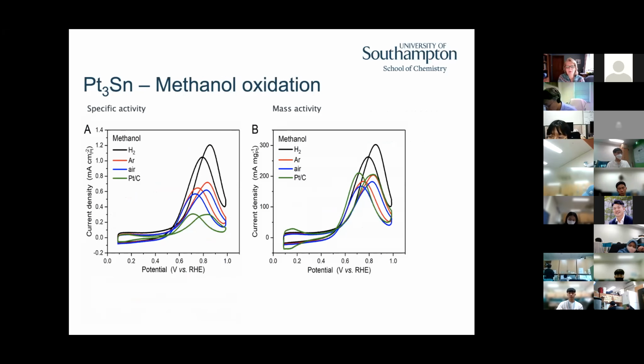Just to show you that we use these materials to look at methanol oxidation. We also looked at ethanol and butanol, and you can see those in that Faraday Discussions paper. But again, you see that as you change the extent of mixing, you pull the onset for the oxidation of the methanol down in potential, right? I don't really want to compare the peaks because I'm now having to worry about mass transport effects as well as just the fundamental thermodynamic effects.